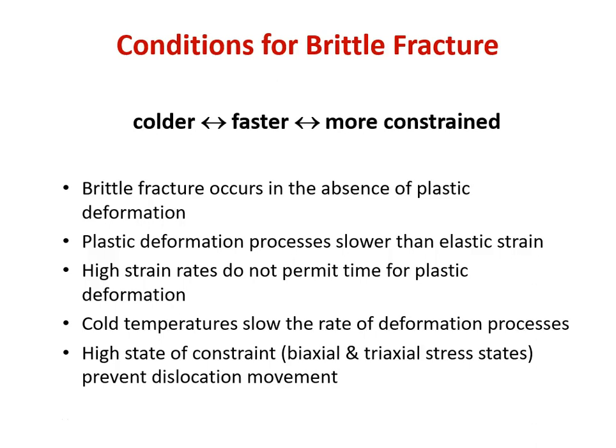And we'll talk about this a little bit more with respect to plane stress and plane strain. Those are more qualitative assessments of the state of constraint or the extent of multi-axial loading that a material can undergo simply because of its thickness. So for any given macroscopic loading, the closer to the center of a real thick piece of material you are, the more effectively you'll be in a multi-axis loading state. If you're way out on the surface, just your conditions of static equilibrium say that you can only be loaded in two ways because obviously you can't impose a load or a stress from the surrounding air. So everything on the surface or anything in a very, very thin material will tend to be in at most a biaxial or uniaxial stress state.